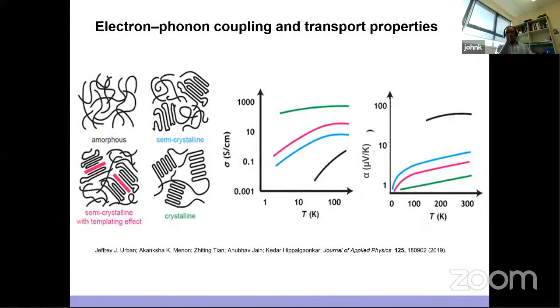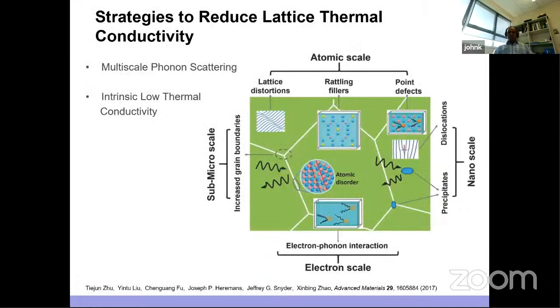Then there's the good old electron phonon coupling, which is also heavily investigated on systems from amorphous to semi-crystalline, mostly inorganic and organic hybrid systems as well. So the transport properties are highly anisotropic in these materials, and sensitive to processing conditions and measurement directions. There are also various strategies used for lattice thermal conductivity, which again look at grain boundary effects and dislocation disorders. So this again highlights how much defects play a role in each parameter.